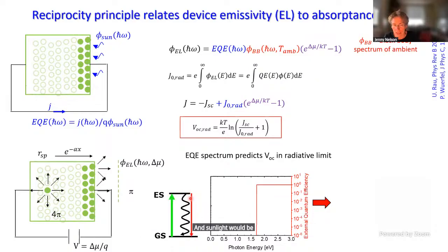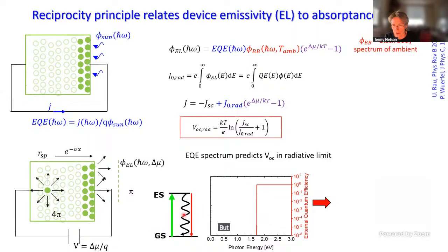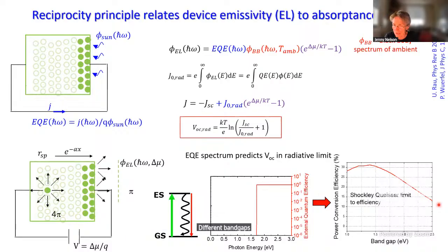We would only have light being absorbed, and some light would be emitted. This can't be avoided. If you're absorbing light, you must emit it. That's where the reciprocity comes from. But all other loss processes are turned off. And then when we have this configuration, we get this Shockley-Queisser limit. It's the same that I showed you before. Different band gaps have a different limiting efficiency.